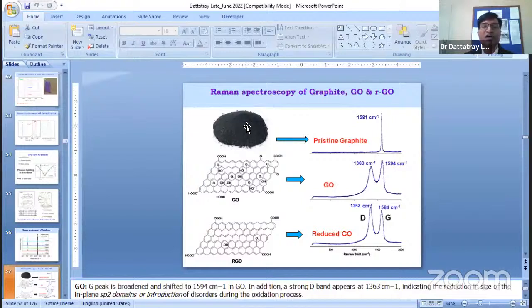The moment, for example, you have graphite, you can just do the continuous Raman spectroscopy, and you will get a single peak, the G band, around 1581 for bulk or pristine graphite. The moment you make it graphene oxide or reduced graphene oxide, you will see a lot of functional groups, right? Defects will be induced in the graphene, right?